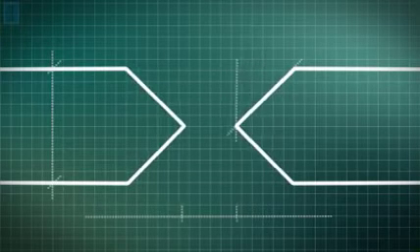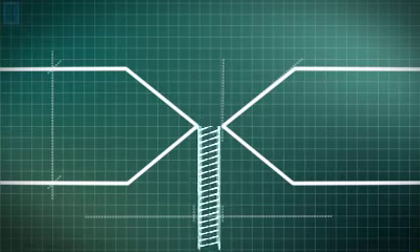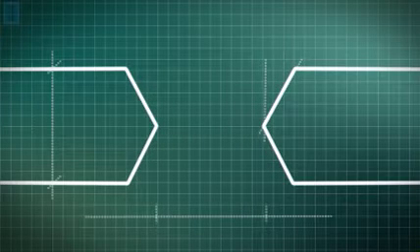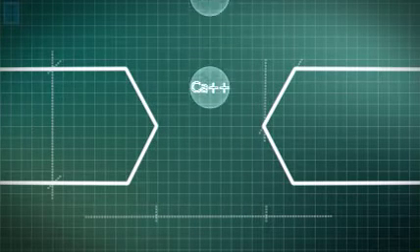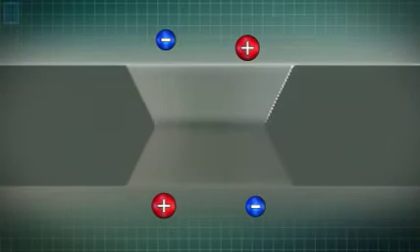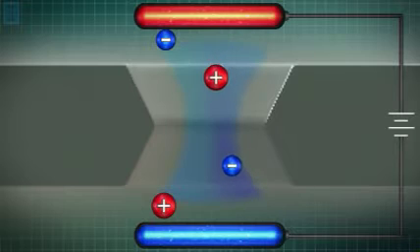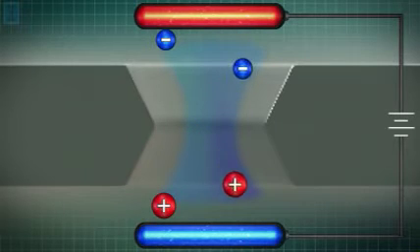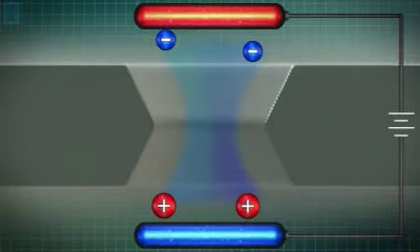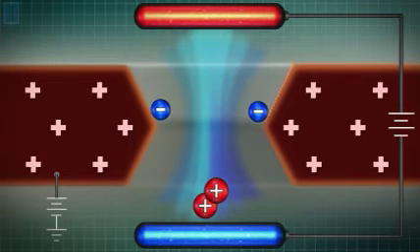Changing certain elements of the nanopore allows for ions, species with charge, or DNA strands to selectively pass through the wafer. For example, we can selectively filter calcium 2+ from sodium 1+ while trapping chloride ions. The filtering process begins by creating a charged membrane, resulting in a field that spans the length of the nanopore. Entities with a net charge will migrate through the pore's field toward the corresponding opposite charge. Alternatively, the electrical conditions of the membrane can be changed to create a stronger field gradient in the membrane pore.